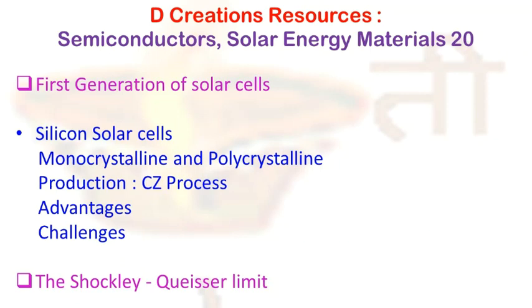The process to prepare these solar cells is also tedious. So of course we want to prepare a PN junction based on silicon, and usually monocrystalline silicon solar cells involve growing silicon blocks from small monocrystalline silicon seeds and then cutting them to form monocrystalline silicon wafers. So these are fabricated by a process called CZ process or Czochralski process. And monocrystalline material is widely used due to its high efficiency as compared to multicrystalline material. But there are technological challenges associated with this process, because this requires stringent requirements of material purity. Then there's high material consumption during the cell production or manufacturing process, and the limited module sizes composed of these cells.